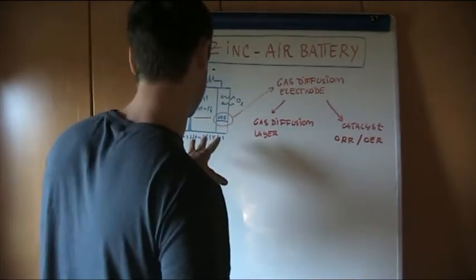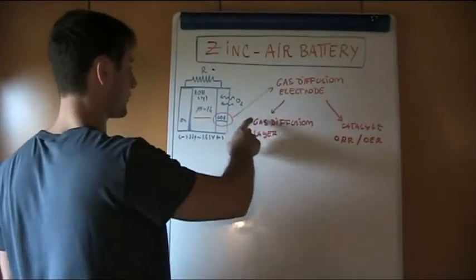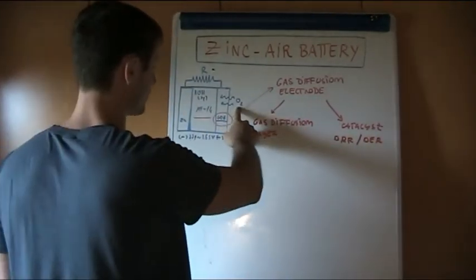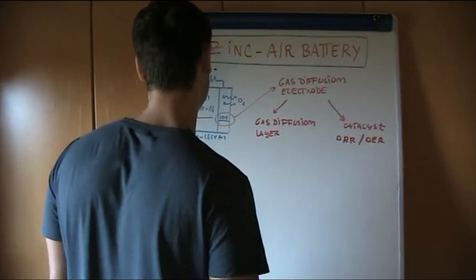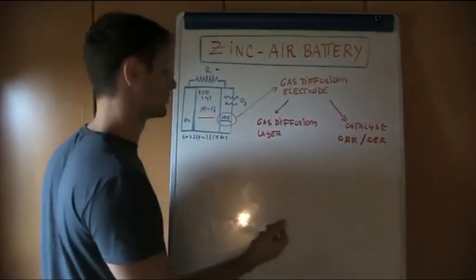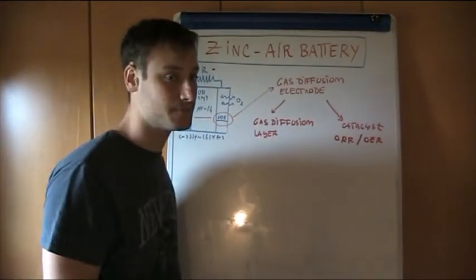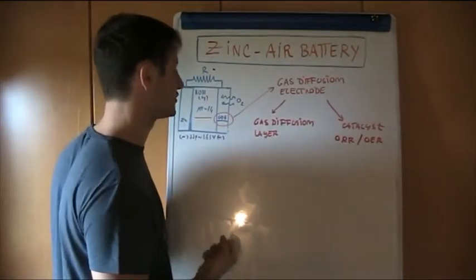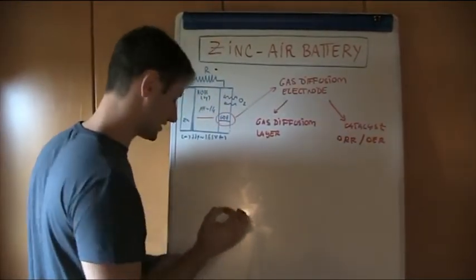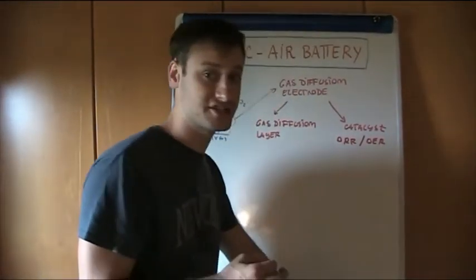So we have defined the diffusion of oxygen from outside, which is one of the problems concerning the use of these types of electrode. But since this is a porous structure, we can sometimes even have evaporation of water, so a small amount of water can escape from the pores of the GDE. And so we can have a change in the concentration of the electrolyte, with changes in viscosity and conductivity that can cause problems.